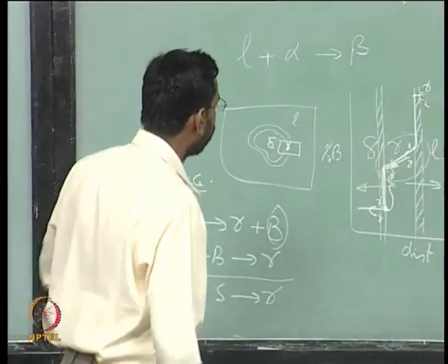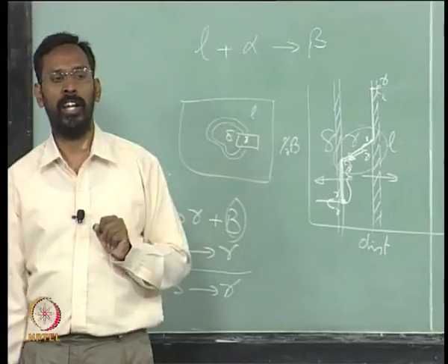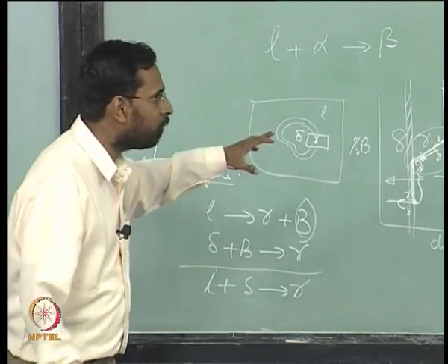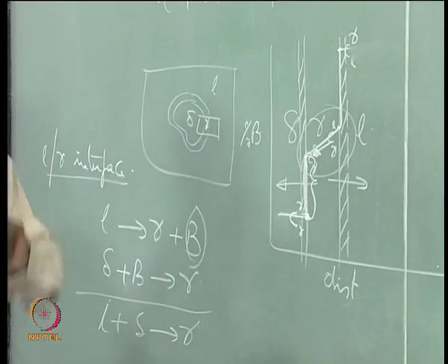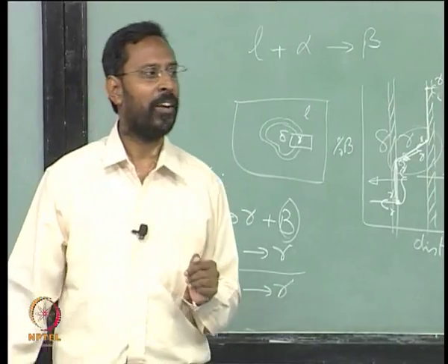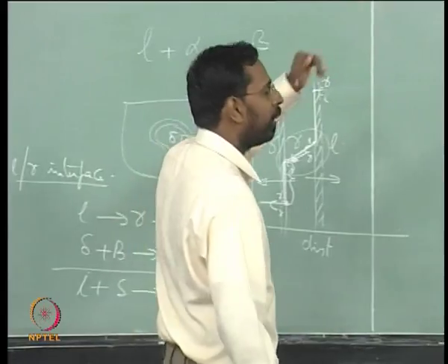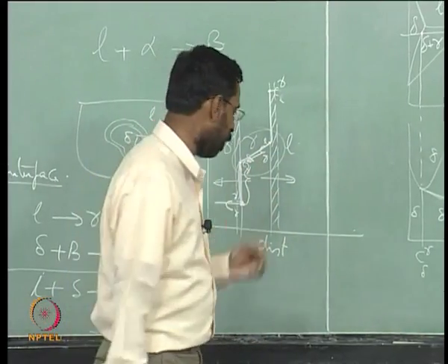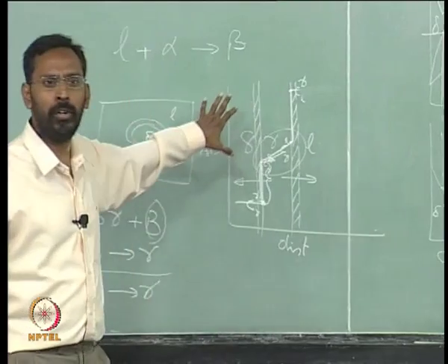A peritectic reaction needs a diffusion of atoms through that solid layer, and once you understand this, you would see that it is very easy to understand the peritectic transformation. And that is the reason why sometimes, if I cool a system very fast, you may not see a peritectic reaction taking place. For example, there are what are called metastable phases. Is this very clear to you now?